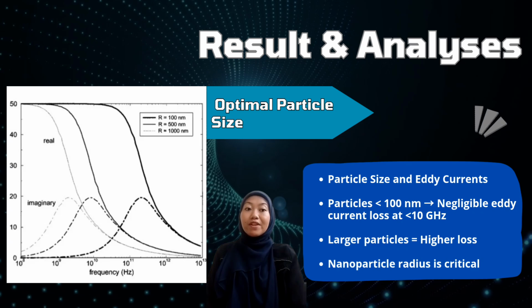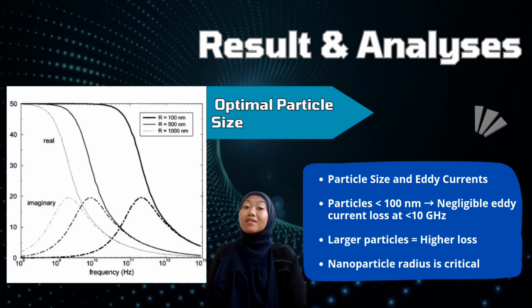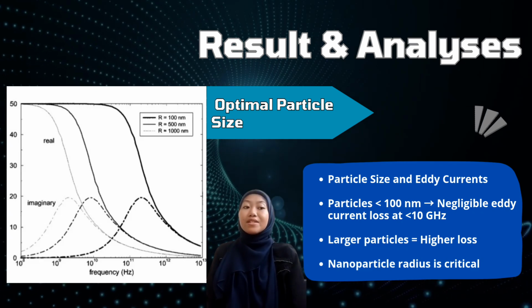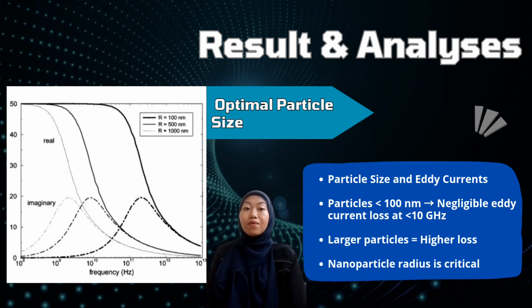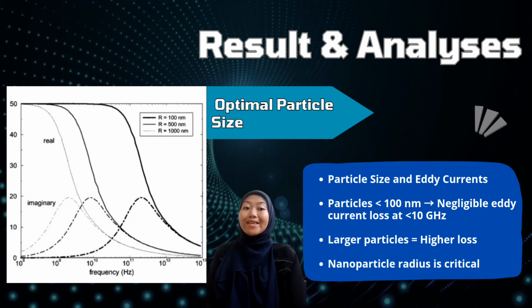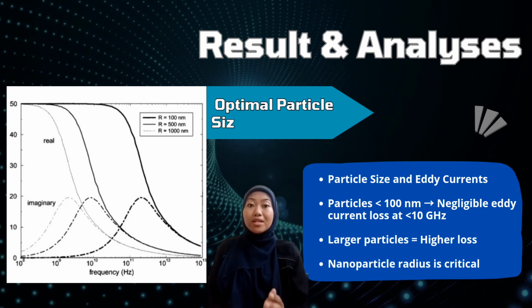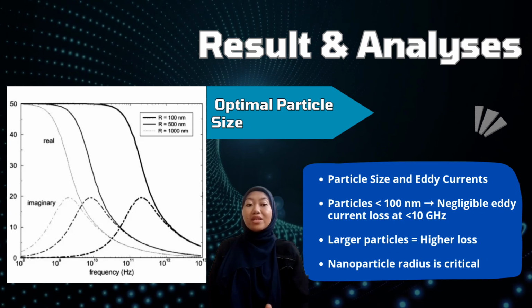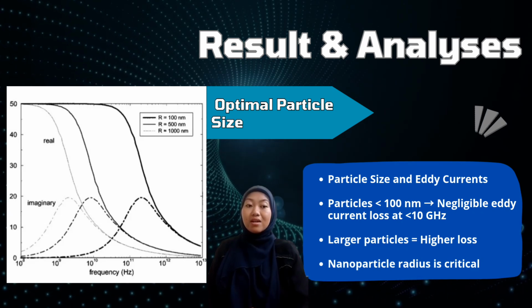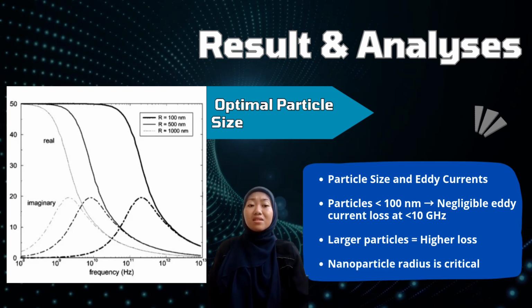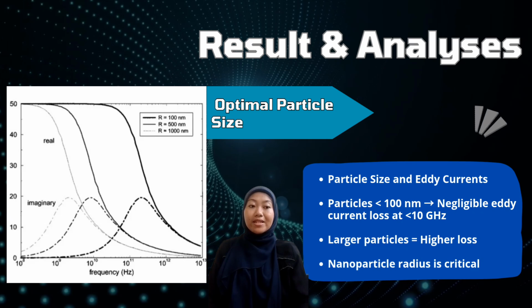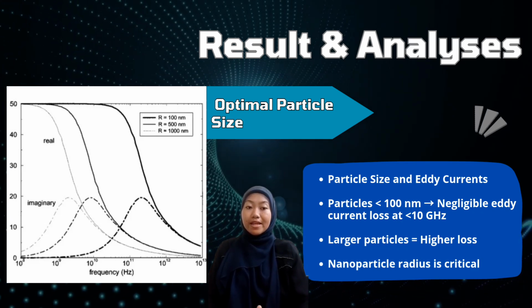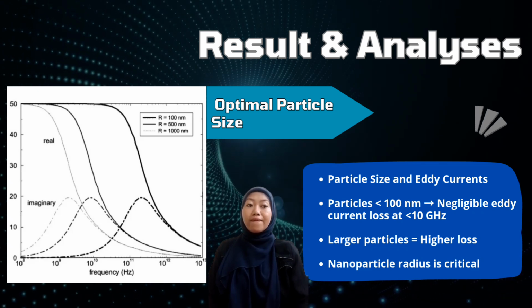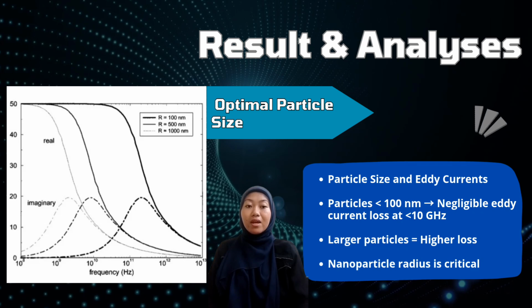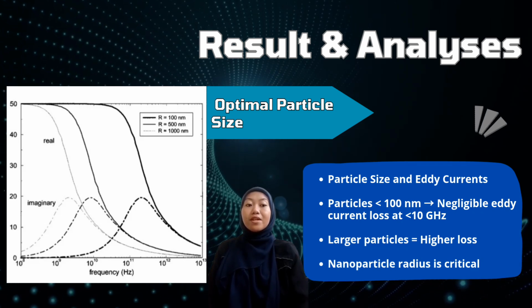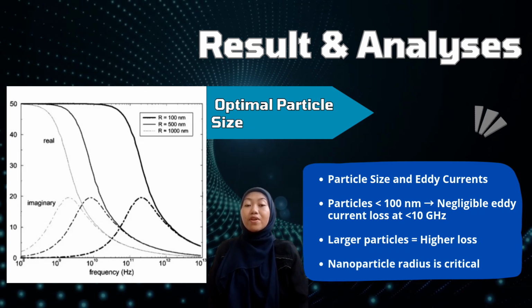Particle size. One of the most significant findings relates to the particle size. As particle size increases, eddy current losses also increase. This is because larger particles allow more surface area for induced current to flow, which absorbs magnetic energy. This study found that particles smaller than 100 nanometers in radius exhibit negligible eddy current losses below 10 GHz. This means that keeping particle size within the nanoscale is essential for applications like RF inductors and sensors. This finding sets a practical design constraint. If the particle radius exceeds 100 nanometers, magnetic loss begins to significantly degrade performance at target frequencies.